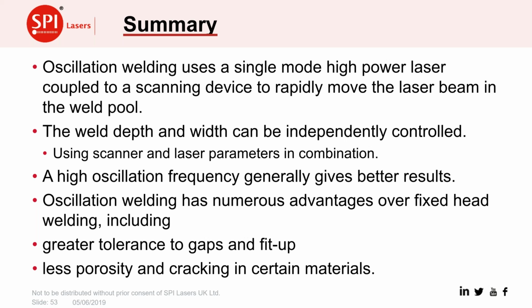And by using the scanner and the laser parameters in combination, we're able to independently control the weld depth and the weld width, which gives us really good results for a wide range of applications and allows us to get into situations that with just the standard fixed head welding would not be able to be achieved. So we like to run the oscillation frequency quite high. That keeps the weld pool moving and generally gives us better results.